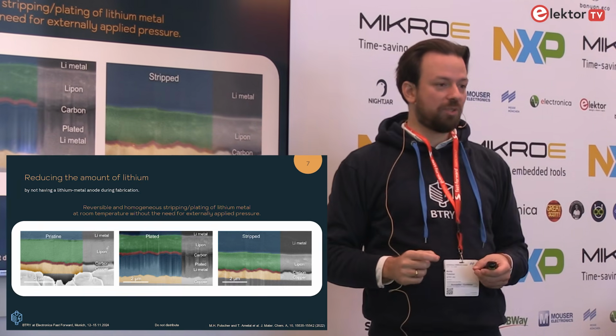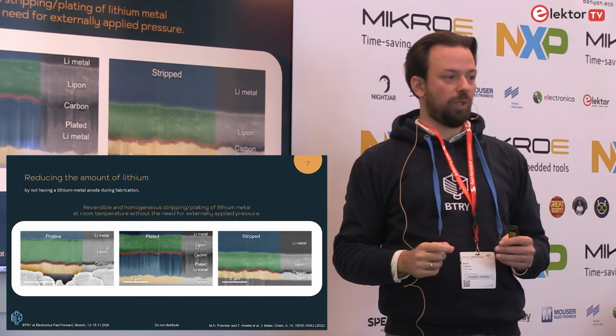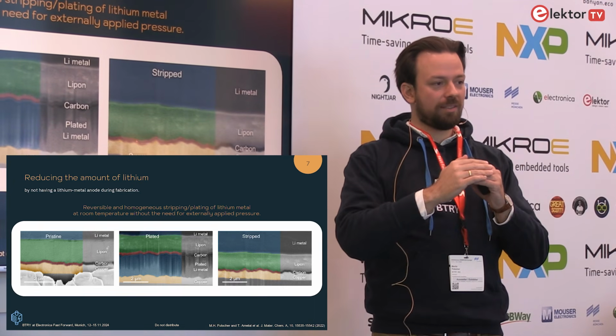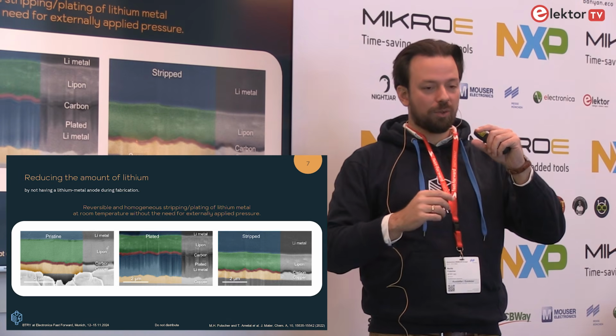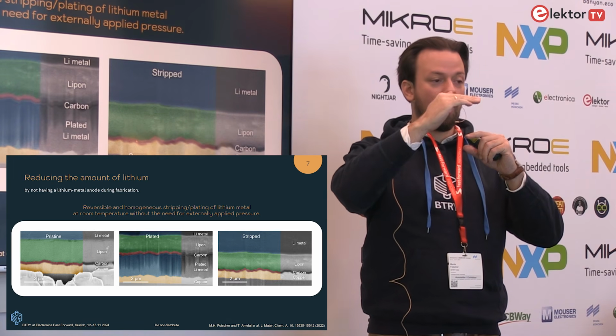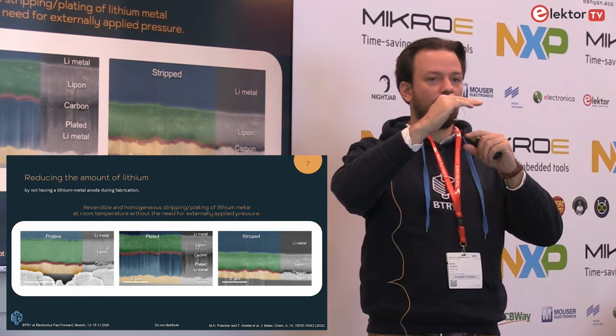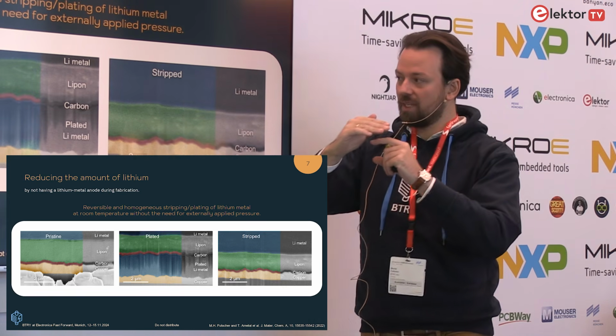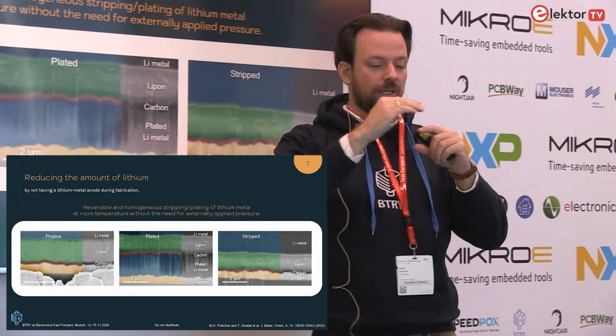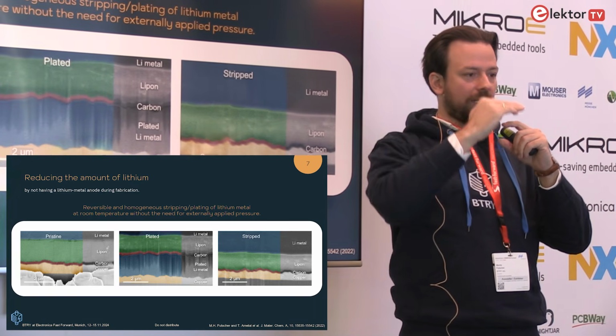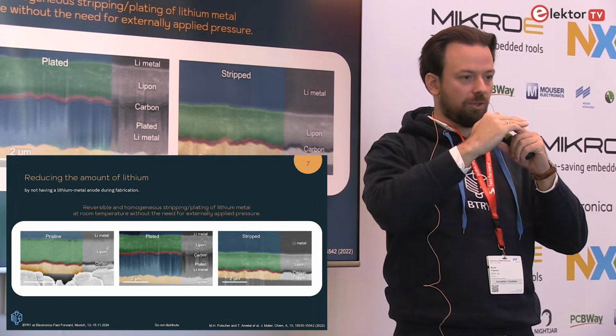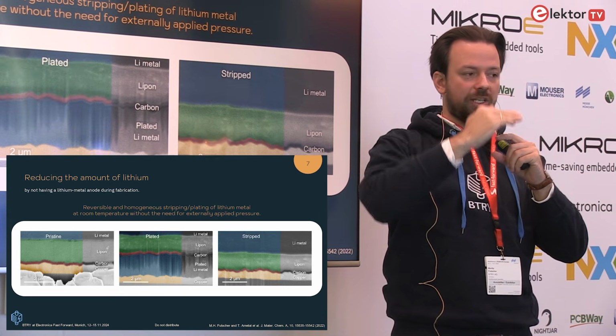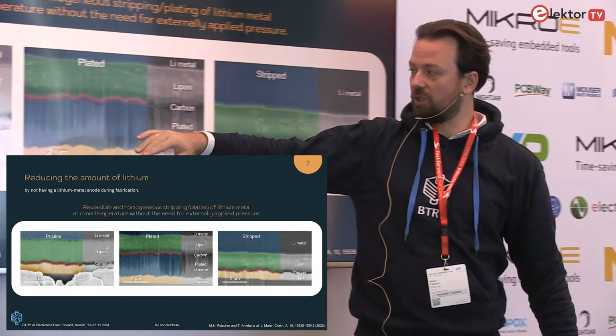We are able to produce them anode-free. That means that we don't have an anode as we fabricate. So during the fabrication, we have a cathode, we have the separator, but no anode. The whole lithium for the anode is in the cathode itself. And for this, we need very homogeneous growth of this lithium metal. So it's really growing and dissolving again in the process of charging and discharging. And this is what you can see here.